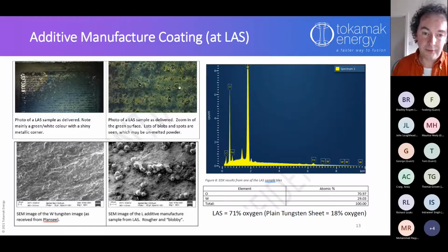If we zoom in, you can see these blobs. It's almost like a series of welds, but there are these little white spots on top, which are probably unmelted powder. This is a scanning electron microscope picture of a plain sheet of tungsten. So you can see it does have features, but it's pretty flat. And this is the additive manufacture surface, which isn't so flat and has these blobs here. These are about 50 microns across, which is better. The powder was 50 micron powder, so these are probably unmelted blobs of the tungsten powder, which has ended up sitting on the surface.